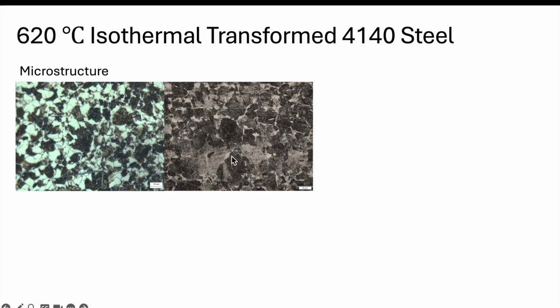So these are the microstructures, again, from 2 different samples. One thing you'll notice here is you'll see distinct regions. In this case, we have a lighter region over here, over here as well, the shading looks a little different, but that part isn't important. It's a lighter gray here, maybe almost like a bluish tint over here. These are the ferrite that forms first, and then the darker regions that you see, here, here, here, and also in these regions over here. This is the pearlite, and so we expect to see ferrite, the lighter regions, plus fine pearlite.